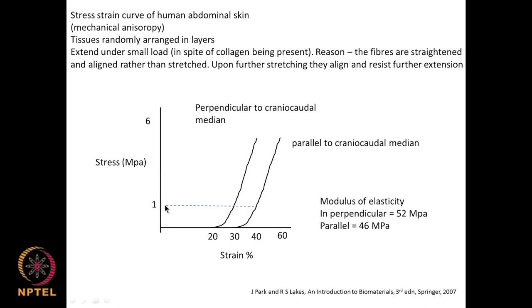If you apply a stress of 1 megapascal, it may have around 25 or 26 percent strain when perpendicular to the craniocaudal direction, and if the stress is applied parallel, you may have almost 40 percent strain. So both are very different.